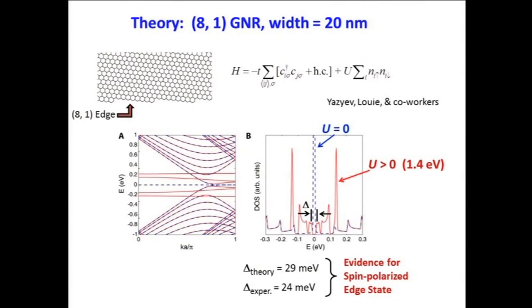And I just want to mention to you what the physics is. What's happening as they turn on the electron-electron interaction is that it causes the edge state to become magnetic. So each of the edges becomes magnetic. They become antiferromagnetically correlated, and that antiferromagnetic correlation causes this gap right there to open up. So that's what happens in the model. We actually saw that same gap in our experiment, but in the model, it arises due to magnetism, and we have not actually measured magnetism in our experiment. We just see the gap.